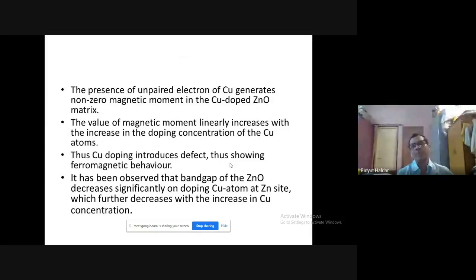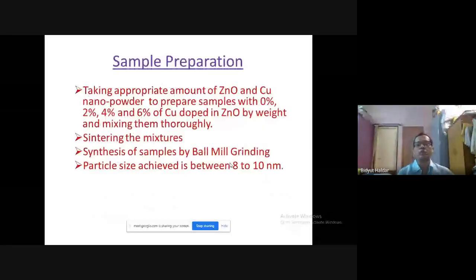The value of the magnetic moment linearly increases with the increase in the doping concentration of copper atoms. Thus, copper doping induces defects, showing ferromagnetic behavior. It has been observed that the band gap of zinc oxide decreases significantly on doping copper atoms at the zinc site, which further decreases with the increase in copper concentration. So with this theoretical calculation behind us, we wanted to correlate with the experimental findings.